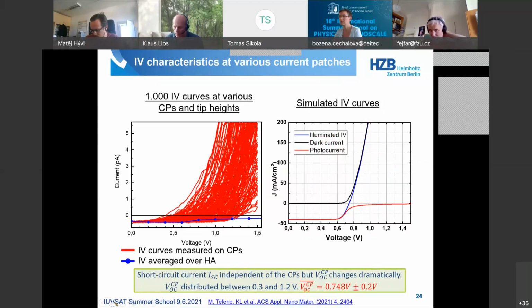And this is the IV curve that we expect. You can see what comes out is this open circuit voltage here of 0.75. And you can see the red curve here. That is the actual photocurrent that has been calculated. And if you compare to that blue curve, you can see it kinks around 0.7 volts. This is exactly right here where it kinks. So it seems to fit what we simulate. So somehow that is extremely important for how that solar cell is working.